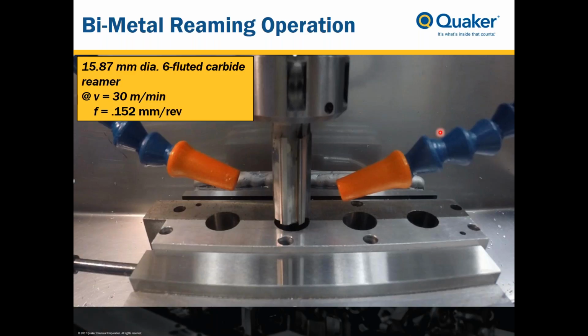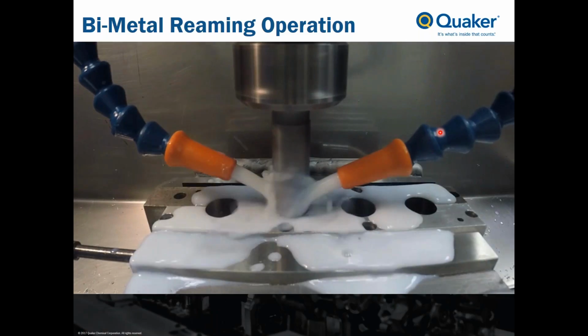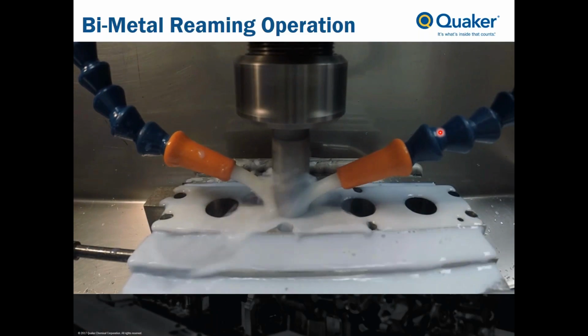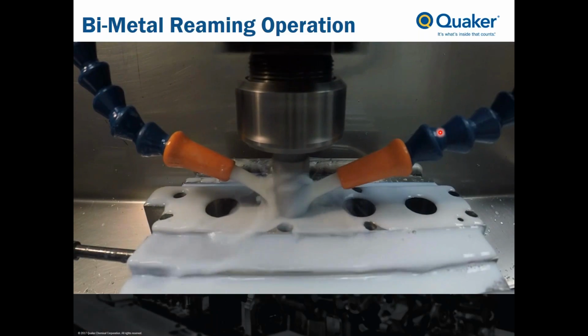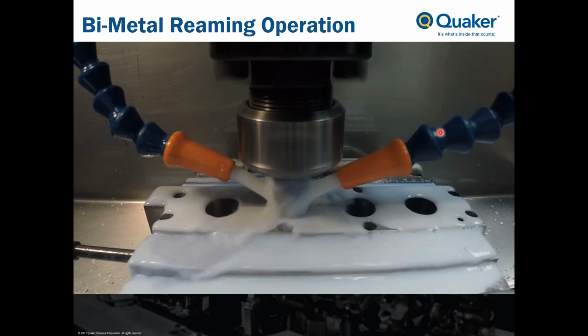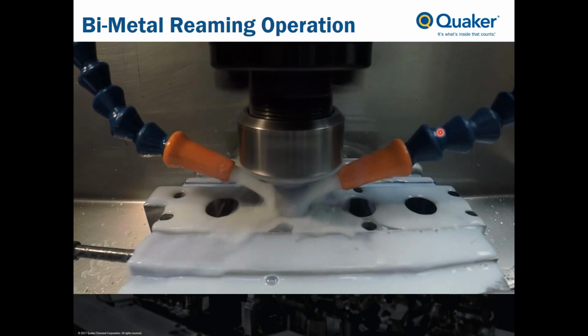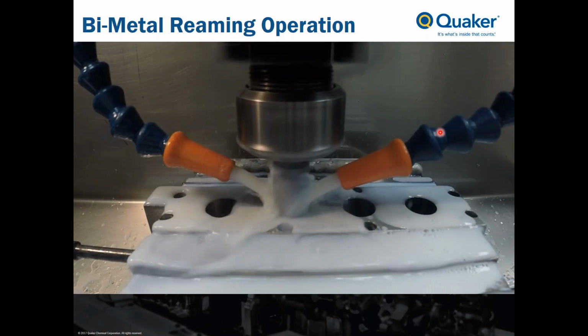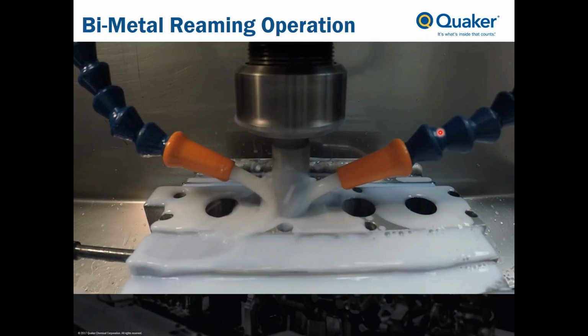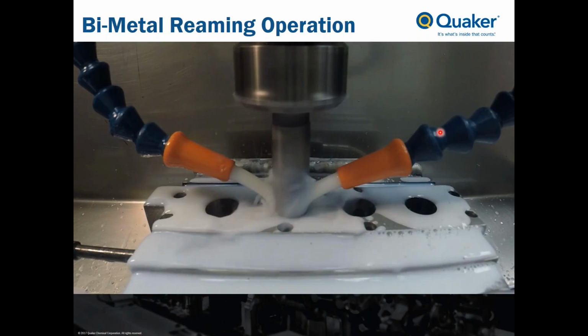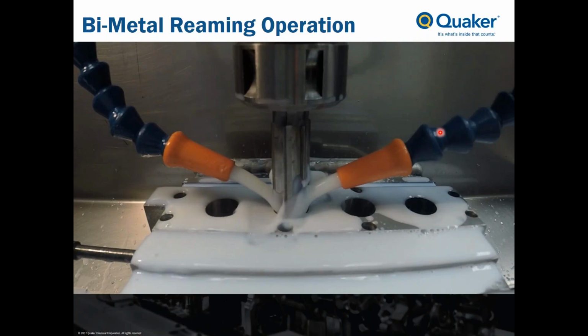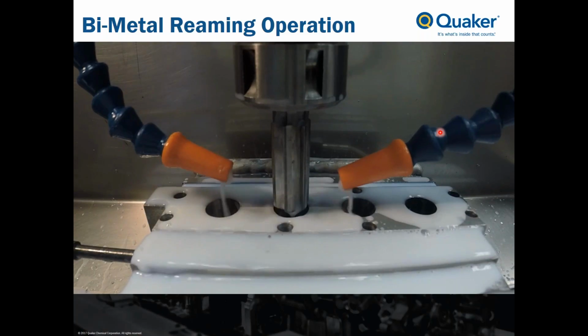So here's a picture on this next slide of the fixturing of the part. This part has four bores that we machine in succession, and I'll just show you a very brief video of the actual reaming operation. The coolant is external. In this case, we're using a very standard semi-synthetic aluminum machining fluid. The rough bore is 15.5 millimeter in diameter. We're using a reamer of 15.9 millimeters, so we're increasing the bore diameter by 0.37 millimeters. And which gives us a depth of cut of a little under 0.2 millimeters. And as you can see, we're using a feed rate down, and we're using the same controlled retraction feed coming out.